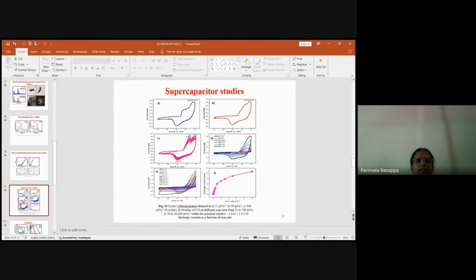Here you can see the current versus potential. Cyclic voltammetry studies were carried out at 25 millivolts per second, at 50 millivolts per second, and at 100 millivolts per second. At 8 different cycles you can see the peak remains as such. The shape does not change here, at about 0.62 volts and 0.91 volts. And as the number of cycles increases to 100, you can observe that the shape gradually changes.